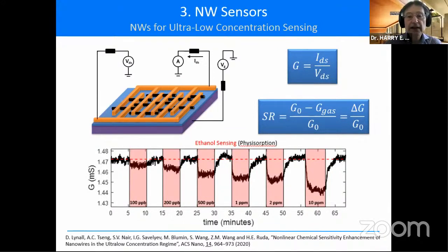So in this case, we decided we would take not just one nanowire, but an array of nanowires, again disposed on a degenerately doped silicon backgate structure with thin oxide. And these are contact printed down on that structure with two interdigitated gold electrode structures. So now we're looking at many nanowires, and so we average that signal out. And the conductance, as usual, is measured as the source drain current over the applied source drain voltage for a given backgate.